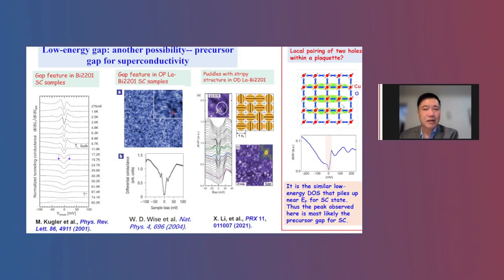Okay, so our key discovery is on the boundary phase of superconductivity, we found this kind of pattern, which has a 4a by 4a. Within each plaquette, we have the 3 unidirectional density bars. And on these bars, we see this density state and a small gap, which mimics that of superconductivity. We think that it is coming either from the consequence of the pair density wave or the local pairing, the precursor pairing. Okay, so this is the first piece of work.